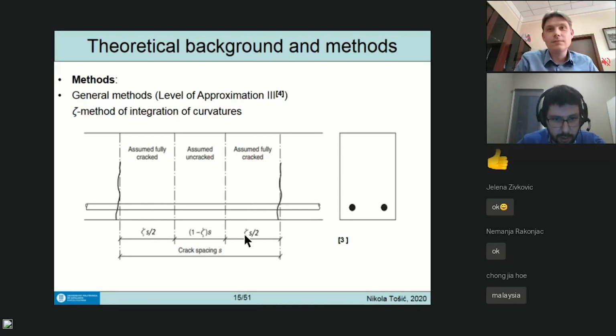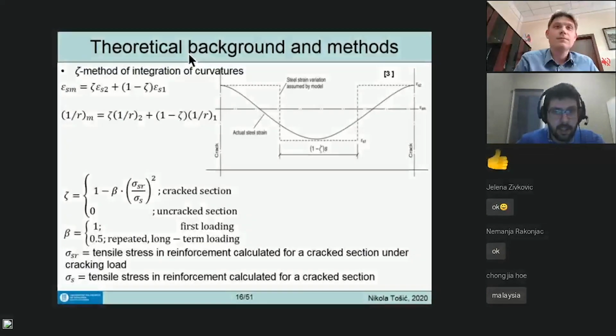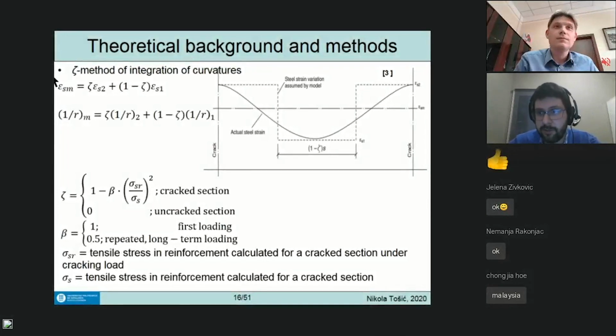So this is the distribution coefficient zeta, which is between 0 and 1. When it is 0, then we are at the uncracked stage. When it's 1, we are at the fully cracked stage. So it's as if we said that these parts, zeta times S half, are fully cracked, and what is left in between is assumed uncracked, for the crack spacing. This is then also transferable to different variables that can be interpolated. We can interpolate strains, as we have here. This is the mean strain in steel, which is interpolated in the following manner. Of course, here again, we have a line that shows the crack. This is the part that we assume uncracked, as well as this one, and what we assumed fully cracked.